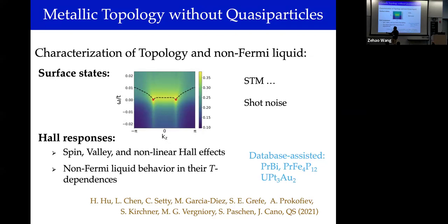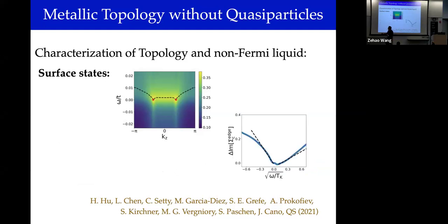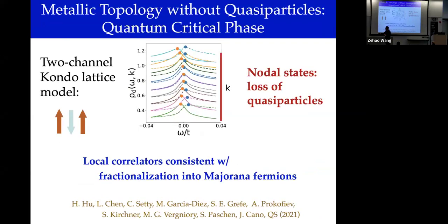But you can actually realize, and this is not our original contribution, this is a contribution that the heavy fermion community has been making over some time already, that, for example, you can think of this local moment as not spins, but orbitals, degenerate orbitals. And then the physics that protects the degeneracy of these two channels of conduction electrons is actually Kramers degeneracy.